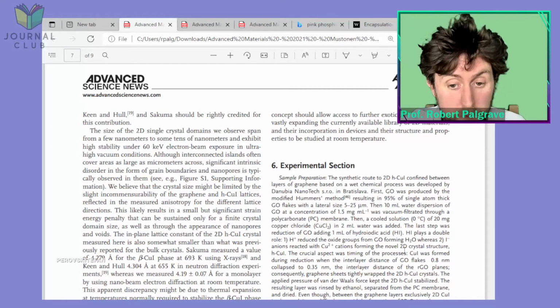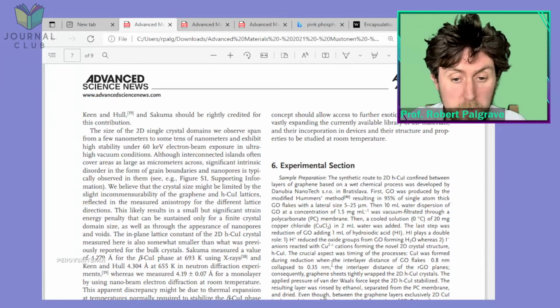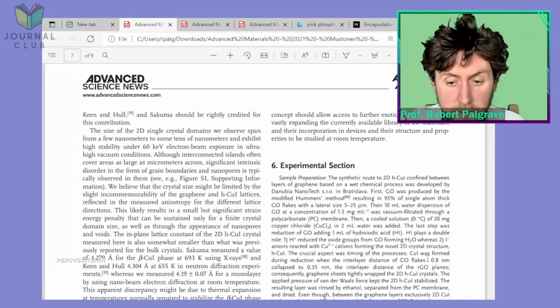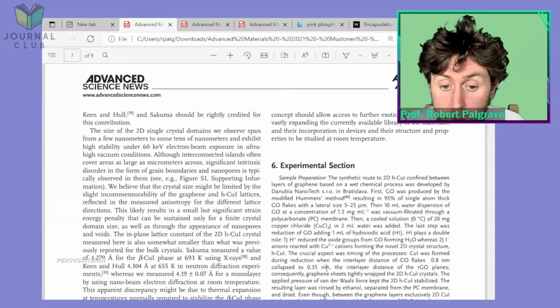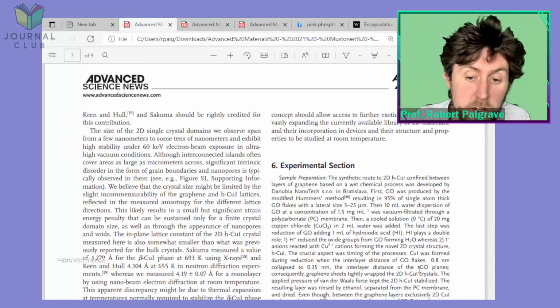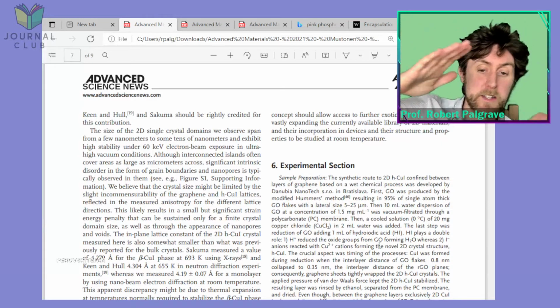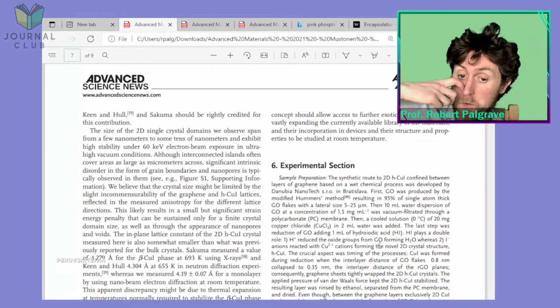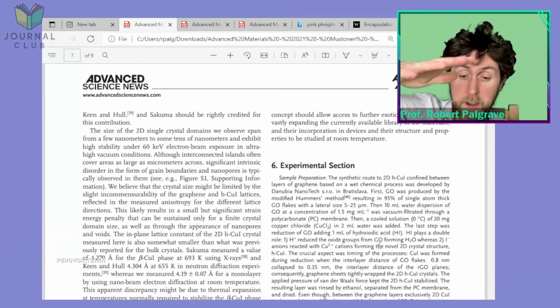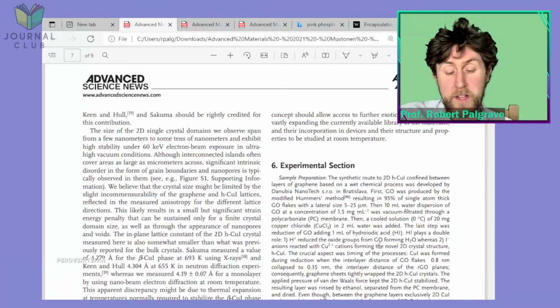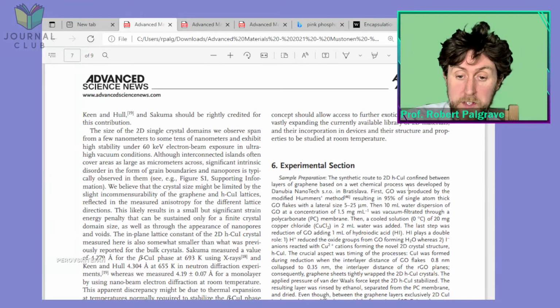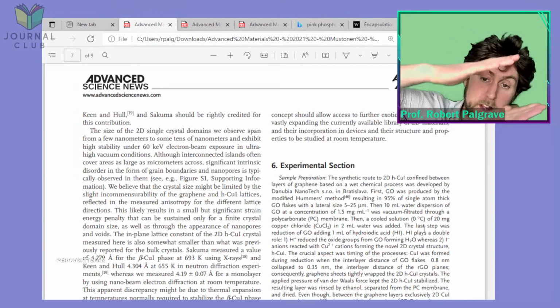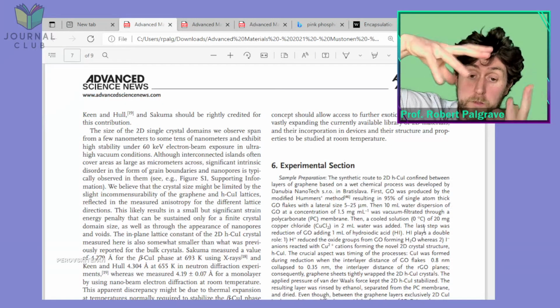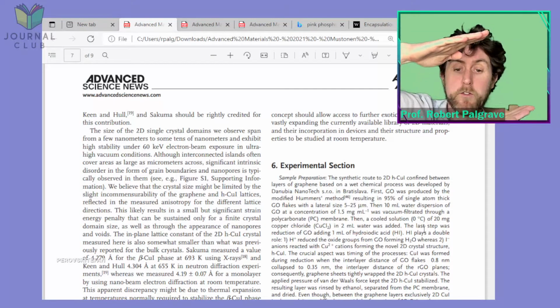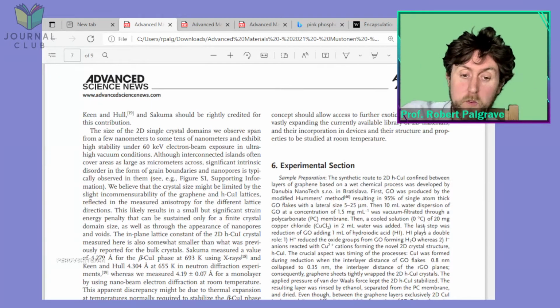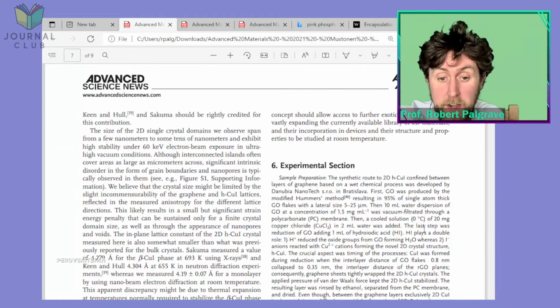The crucial aspect was timing the process. Cuprous iodide was formed during reaction when the interlayer distance of graphene oxide flakes, 0.8 nanometers, collapsed to 0.35 nanometers, the interlayer distance of the reduced graphene oxide planes. Graphene oxide is a layered material itself, but it contains lots of oxygen groups on the carbon layer, which means it has a larger separation. They're saying the separation is 0.8 nanometers between the layers of graphene oxide. But when you reduce it and remove those oxygen groups, you collapse it to a much smaller distance of 0.35, which is similar to what you find in graphite.